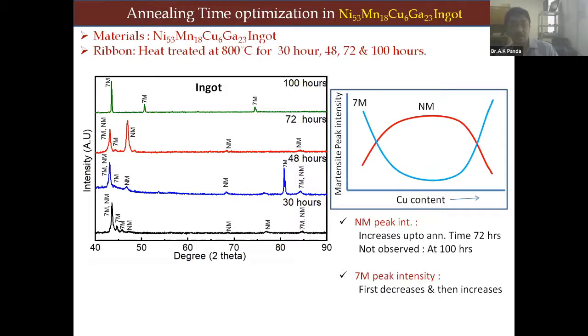I'm not going into details of the annealing temperature. This is how you anneal it. When you anneal it, you can modify from 30 hours to 100 hours, and even with the annealing time, you can modify the modulations, the martensitic modulations, the non-modulated martensites, and so on. The right side is just a schematic to understand what is actually happening. When you go for increasing the copper content, then you can go on increasing the non-modulated martensite, and the non-modulated martensite you can stabilize with annealing up to 72 hours, and when you increase to 100 hours, you do not find it. You find only the 7M. So this is how it happens.